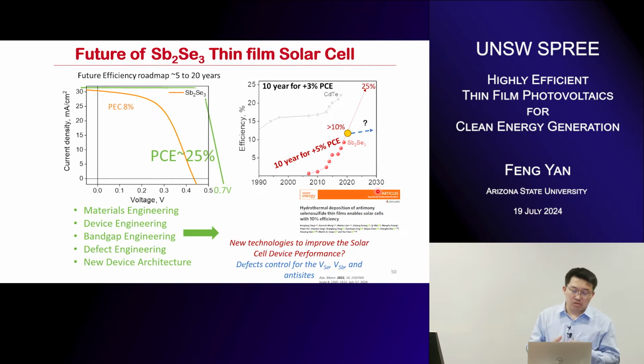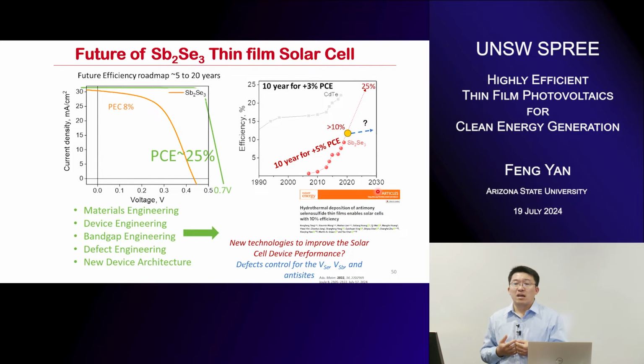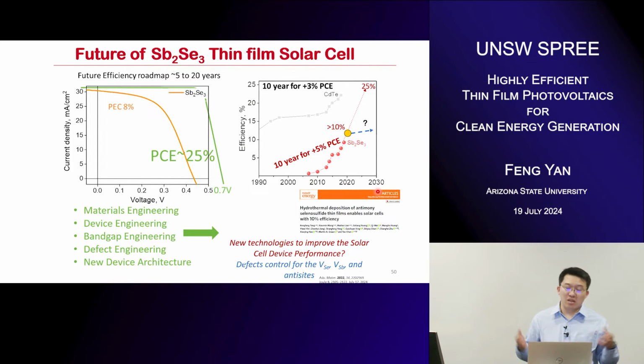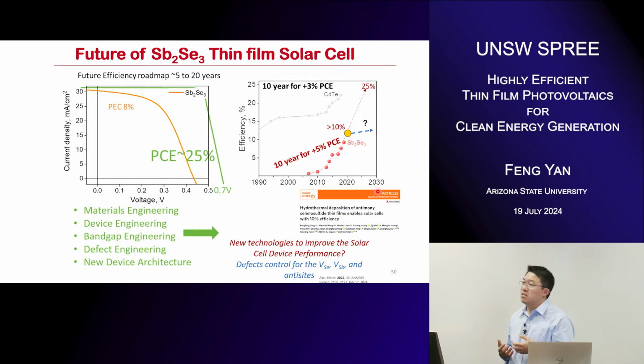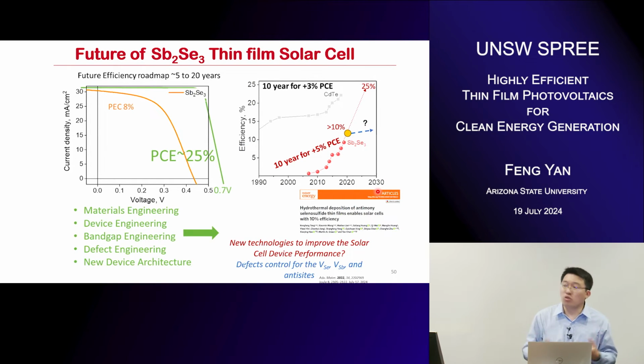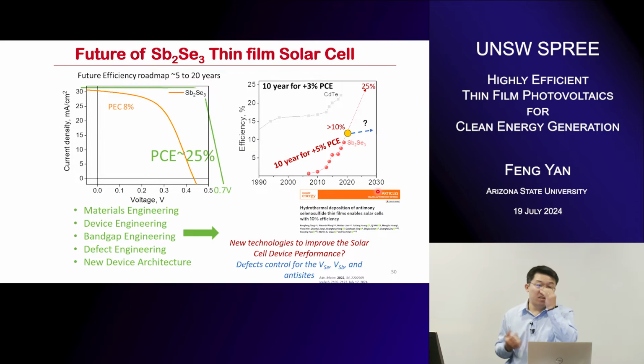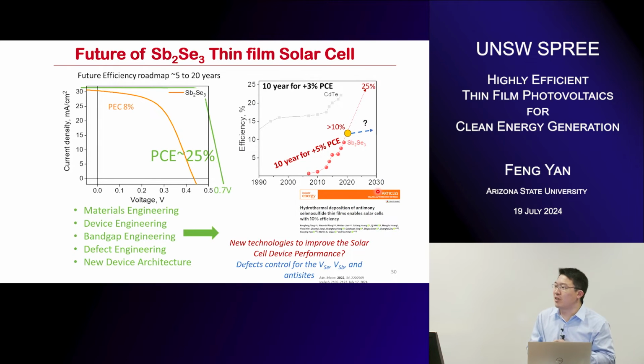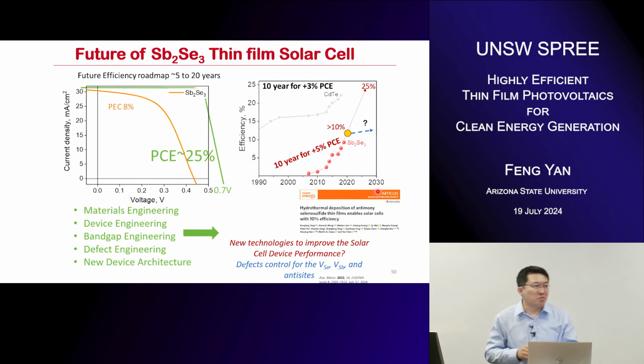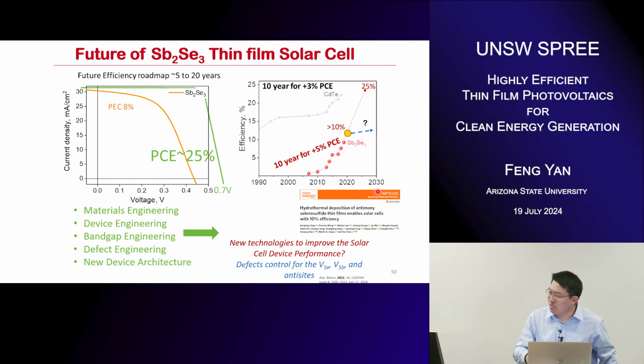Because the crystal structure is different to the cadmium telluride, the inside defect chemistry is different to the cadmium telluride. And imagine that the cadmium telluride incorporates the cadmium chloride treatment, the back contact and the dopings. So I think this is a long run to further improve the device efficiency, but we have a good role model, right? So it will be good to further work in this area to further control the device and the defect. Hope that we can realize a good efficiency soon.